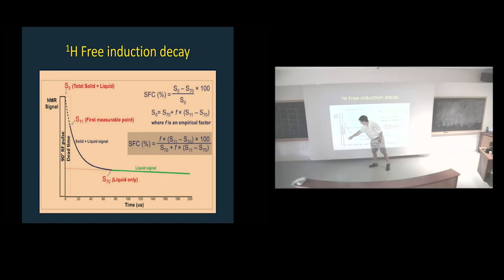You take a signal at about 11 microseconds, then you take another signal at 70 microseconds, and you do a ratio of the two. So basically, solid plus liquid minus liquid is solid. That's it, divided by the total is percentage. Times an F factor, which is, in our area, the venerable so-called fudge factor. And the fudge factor is because you have a dead time of the receiver here, and you cannot measure that point. It can be as high as 25% that you multiply it up. And then you determine the SFC, because the SFC is one of those indicators of macroscopic functionality of your material.